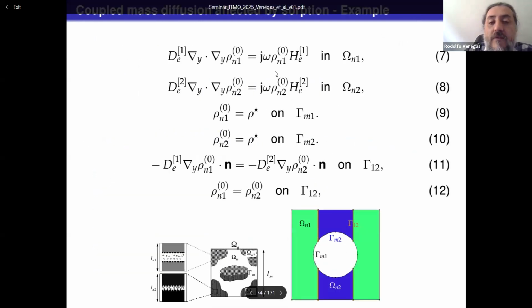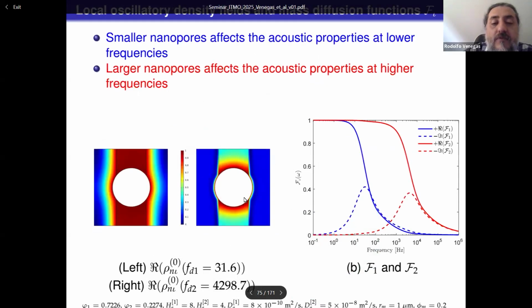But for now, I'll give an example of one particular geometry. So this is a micrometric pore, and one nanoporous patch is omega n1, and the other one is in blue. We formulate and solve this problem numerically to get this type of results with these local density fields. In particular, this means that at low frequencies, this nanoporous patch 1 is all contributing to the mass diffusion through this nanoporous domain, while the other nanoporous patch has a constant density, and at higher frequencies the opposite. So this nanoporous patch is contributing with, let's say, a locally varying density field, while in this other nanoporous patch, everything is confined to this mass diffusion boundary layer, so it's not contributing to the behavior.